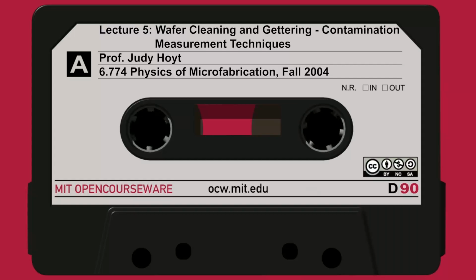Now, if you were to measure your devices, you'd get a distorted curve. Instead of looking just like this with this abrupt drop-off, it looks a little bit distorted from what you calculated in the ideal case. And in fact, this distortion is due to the fact that there is variable interface trap charge. Remember we talked about QIT? We said that the amount of charge in QIT depends on the bias voltage. So as I'm sweeping from right to left, I'm charging and uncharging QIT. And that ends up shifting the curve by variable amounts, so it gets distorted. So the amount of distortion is a way of telling how much QIT you have.